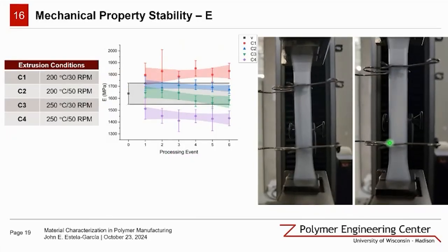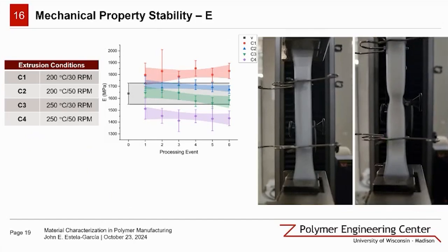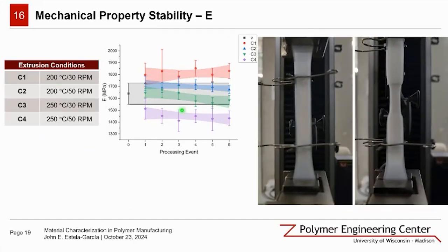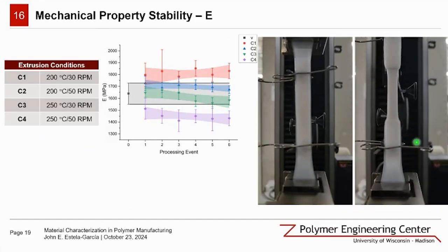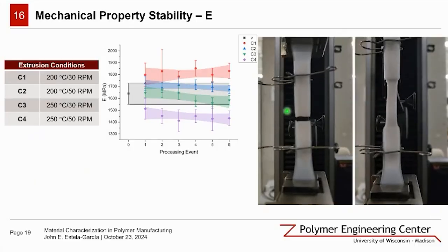What we're observing is two samples of recycled PIR dog bones, where one of them is undergoing strain hardening on the right, and the other one undergoes break on the left. So the tensile modulus data across multiple processing events is marked here. And what we can observe is the relative stability in mechanical performance, but while also understanding that the stability compared to the original values has been changed by the processing conditions, the extrusion conditions of this recycled PIR.